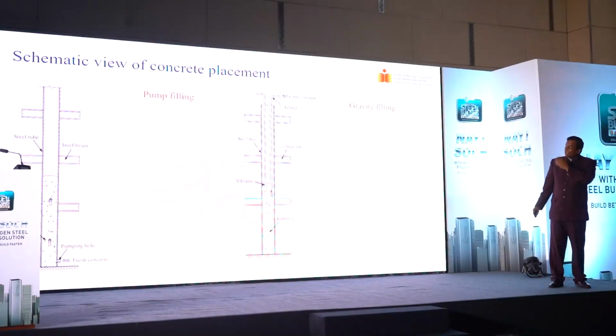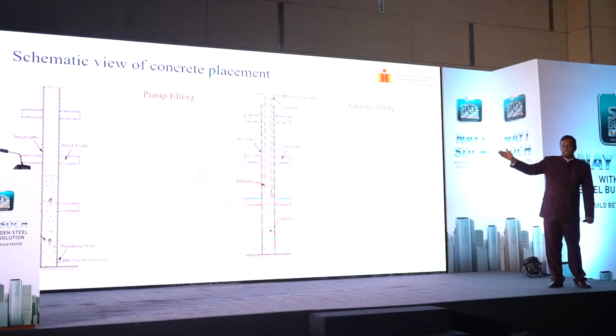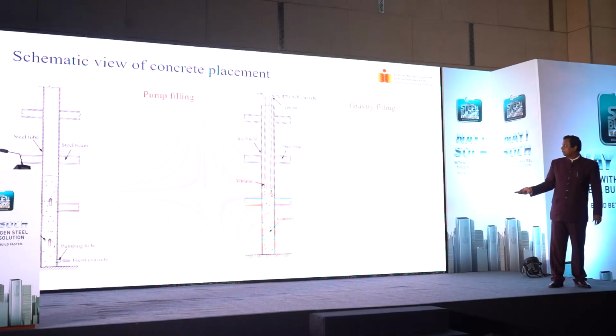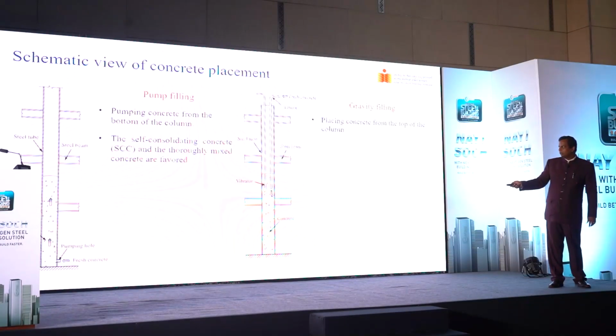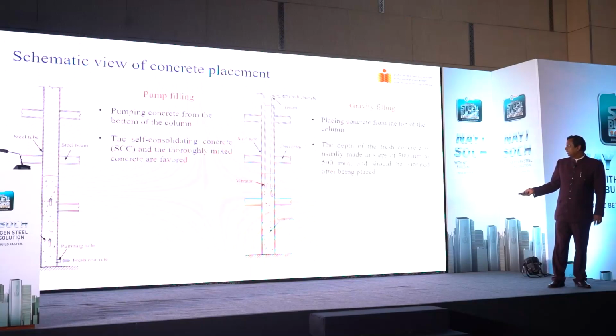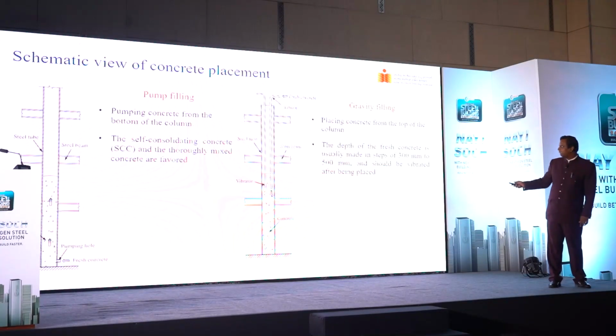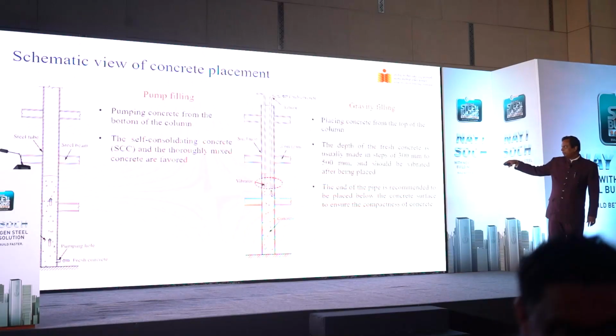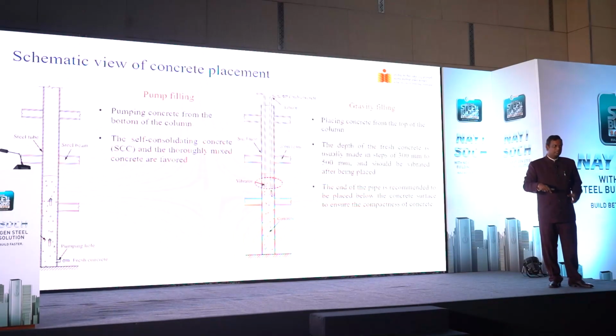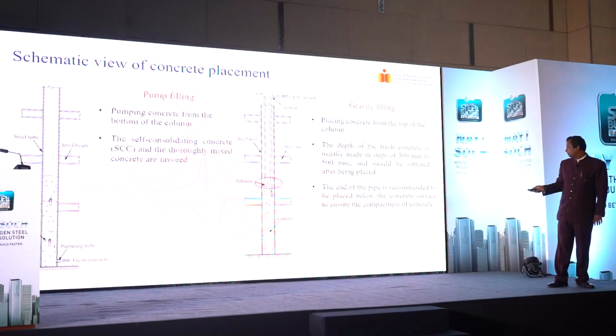This is a schematic view of how concrete would be placed. You can have a steel tube, put a pipe at the bottom, and pump the concrete up to the top, and that needs self-consolidating concrete. But on the right side, you put it in from the top, which is gravity filling. Here you have certain challenges. You have to use a vibrator also. Self-consolidating concrete usually does not need a vibrator. Here you put it in batches of 300 to 500 mm, but you should have a vibrator, and the vibrator has to go a little bit inside, at least 50 to 100 mm, to vibrate the structure so that it gets compacted.